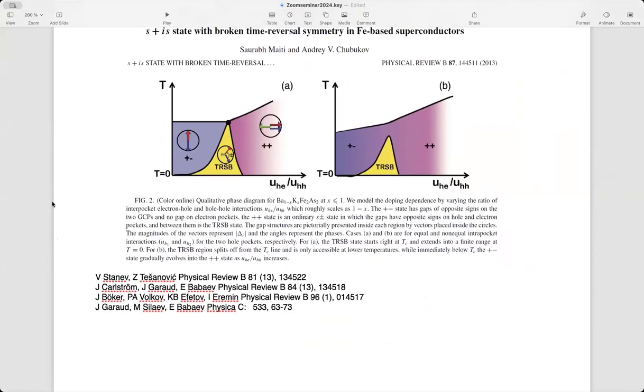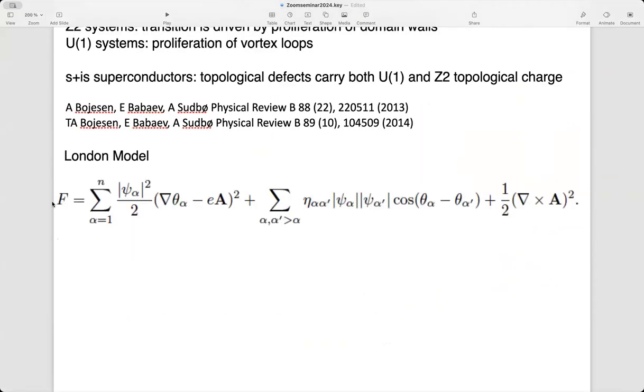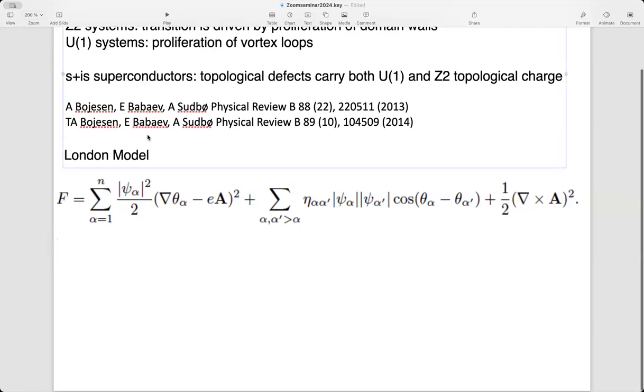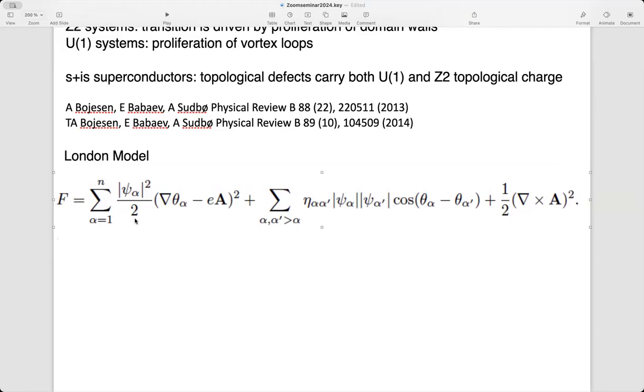considered this problem, and then we have shown that this S plus I superconductor could also have this composite order, basically a four-electron condensate, but one that breaks a discrete symmetry, the two time reversal symmetries. This is where these two works, and essentially, which means instead of two components at the beginning of the talk, one has three components, three phases coupled by the same vector potential, but then this additional ingredient is interband Josephson coupling.